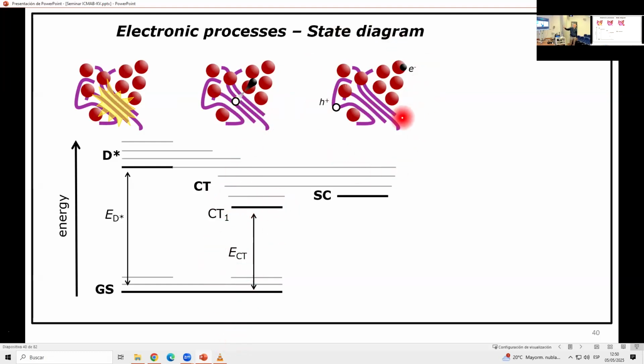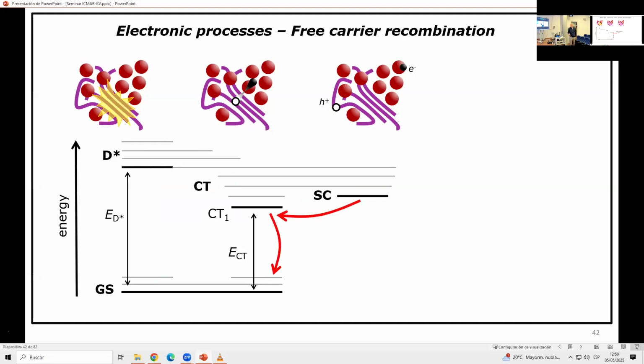And this is what you eventually want, free carriers. But okay, if you don't extract those free carriers, they will not stay in your material forever. They will travel around, see each other at the interface, meet each other, and then decay again via such a CT state. So that's why this interfacial state is very important, because you go basically through it twice. Once you make charges, and when the charges are made and are not extracted, and they meet each other, you're again at such a state. So the feature which makes this state important is that the electron can fall into the hole. So it's coupled to the ground state, which it is because we saw it can absorb light and it can also emit light. So this is what you want, this is what you don't want.